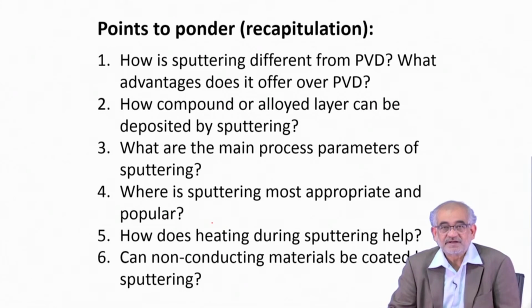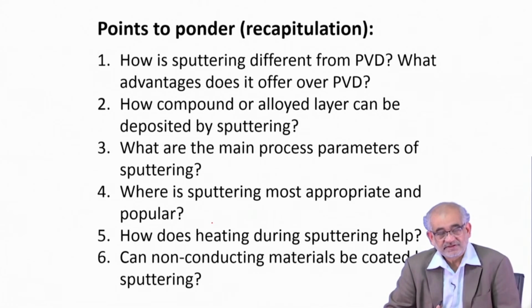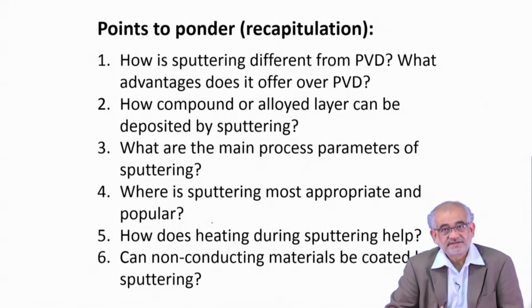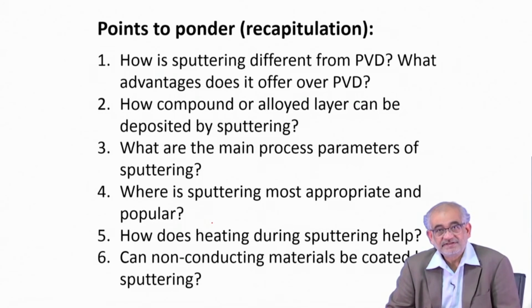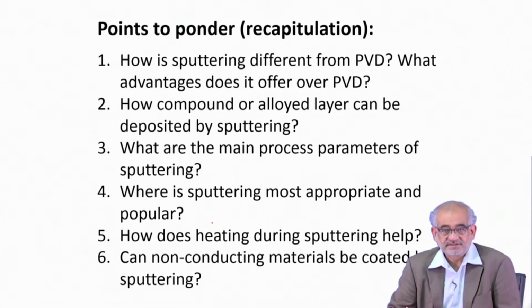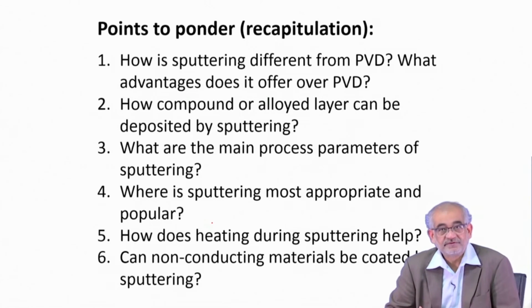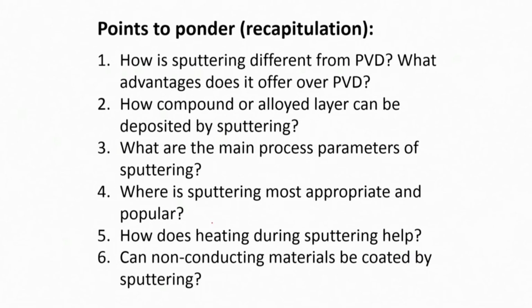The typical process parameters would be the distance, the density of the plasma we create, whether we are using any auxiliary heating process to heat the substrate during deposition. Then obviously the material that we use, its vapor pressure, melting temperature, vaporizing temperatures, and so on.